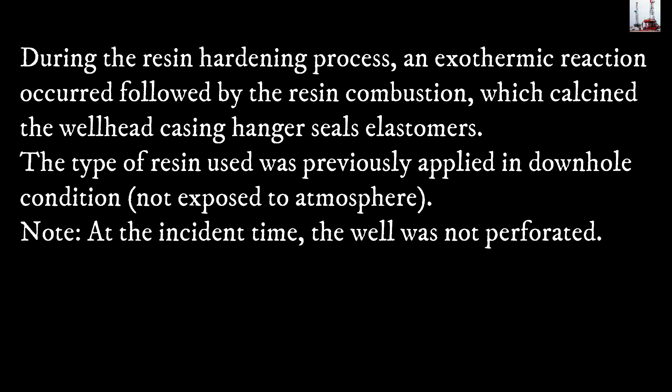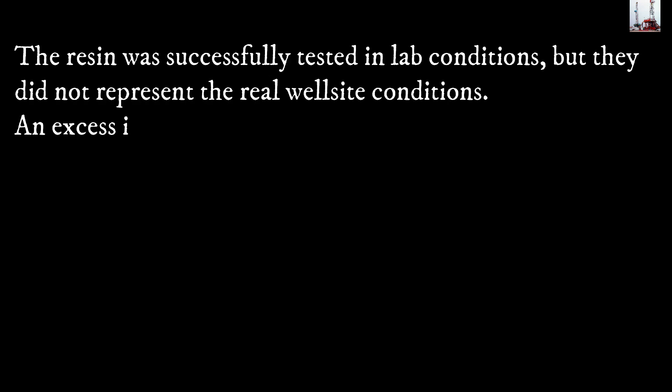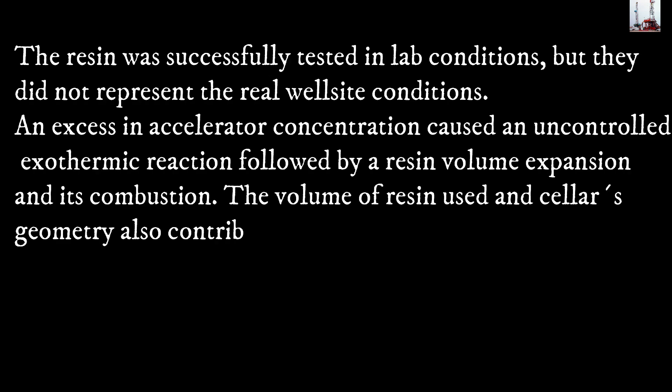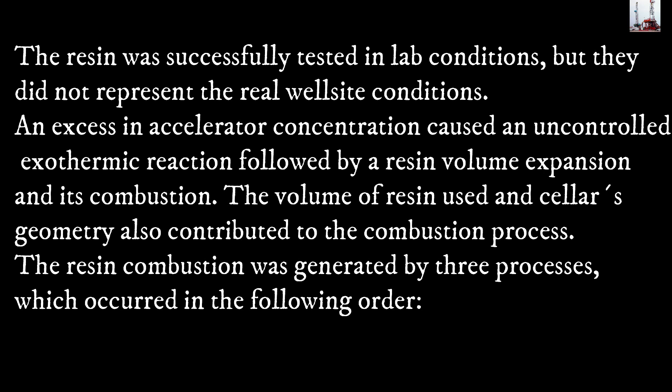Note: at the incident time, the well was not perforated. The resin was successfully tested in lab conditions, but the lab conditions did not represent the real well site conditions. An excess in accelerator concentration caused an uncontrolled exothermic reaction followed by resin volume expansion and combustion. The volume of resin used and the cellar's geometry also contributed to the combustion process.